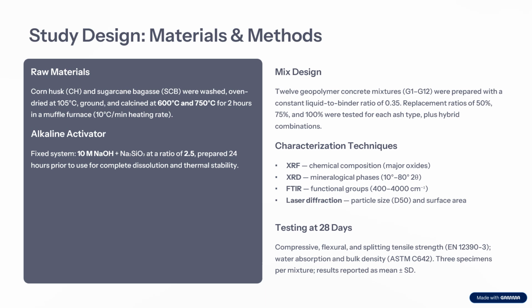For mix design, 12 geopolymer concrete mixtures from G1 to G12 were prepared with a constant liquid to binder ratio of 0.35. Replacement ratios of 50%, 75%, and 100% were tested for each type, plus hybrid combinations. For characterization, we use XRF for chemical composition, which measures oxides, XRD for phases, and FTIR for functional groups from 400 to 4000 centimeter minus 1. We also use laser diffraction for particle size, D50, and surface area.